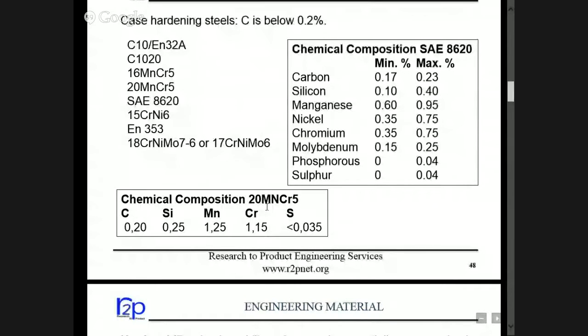So in average loading gearbox shafts of gear, 20 MnCr5 is a very popular and cost-effective solution. This is available at a rate of maybe 60 rupees per kg. And if we have further highly loaded gear shafts, then it is recommended to go for 8620 because it has moly also and nickel also. Molybdenum is added for increasing hardenability, and nickel is for increasing the toughness of the core. So this is the difference between 20 MnCr5 and 8620.